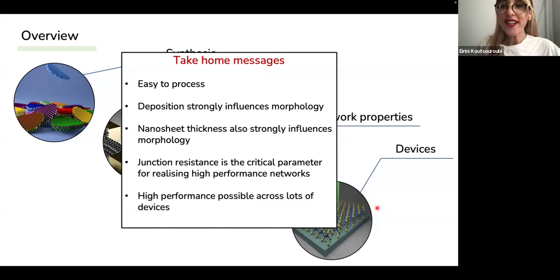Great. And one last question. When different atoms are used for intercalation instead of lithium, how do the surface and electronic properties of the nanosheets evolve? Oh, so this is why we actually use the bigger cations, because we want to minimize charge transfer from the cation to the crystal itself. So the larger the cations, then the fewer will actually go in, and the lower the amount of charge transfer, and you can retain the properties of your nanosheet without actually changing them.